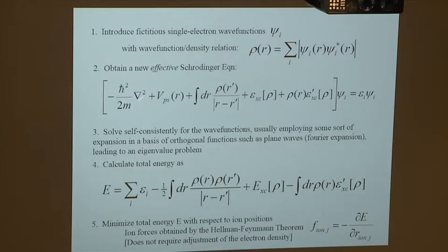The outcome is, after all of this, which is done in normal kinds of numerical ways, that if you do numerical computational mechanics, you would say, well, let me expand these in Fourier series or something like this, and then try to solve this, where these are approximated by Fourier series with some coefficients. At the end, you finally get an energy for the total system, and now you have the energy of the system. And this is fundamentally, if we have the energy, we can say things about how the energy changes when we stretch the material, when we try to create a surface.